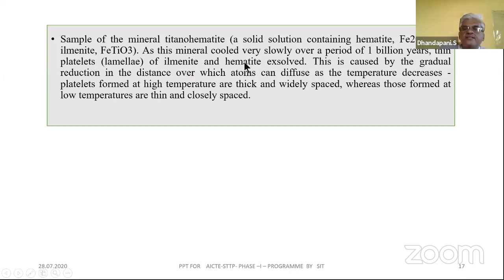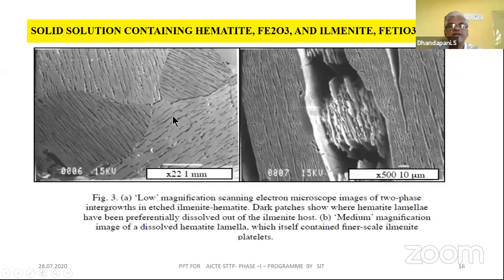One is ilmenite and another is hematite, and this is caused by the reduction in the distance over which atoms can diffuse as the temperature decreases. Plates formed at high temperature are thick and widely spaced, whereas those formed at low temperature are thinner. During cooling, the atoms move over large distances when the temperature is high. If the temperature is high, the plate thickness is higher, and when the temperature is low, the plate thickness is lower. Based on that the structure was formed, and this was explained for magnification purposes.